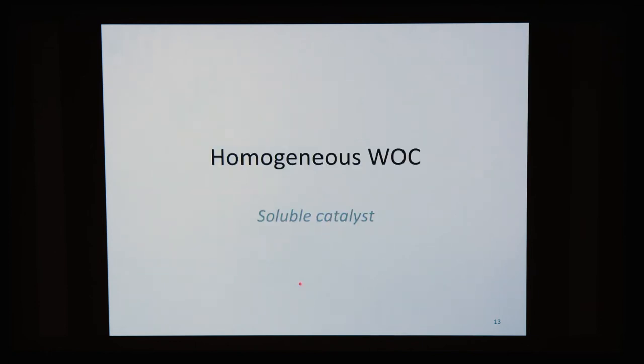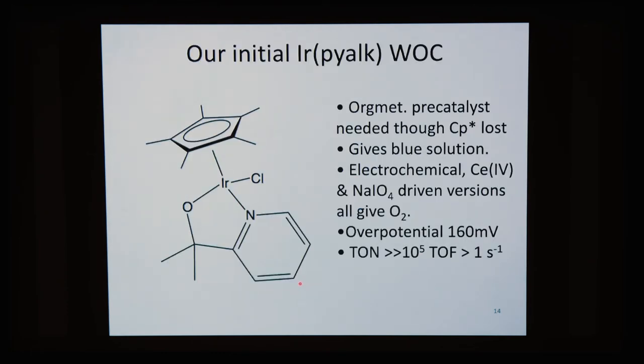And so this brings us to the homogeneous water oxidation catalysts depending on this ligand system. And our initial pi alk iridium system had a CP star and a chloride as co-ligands. And curiously, on oxidation, the CP star is burned off and lost, and we get a blue solution, which is a coordination complex. And we can make it electrochemically with cerium-4 oxidant or sodium periodate oxidant, and in all cases, oxygen is produced.